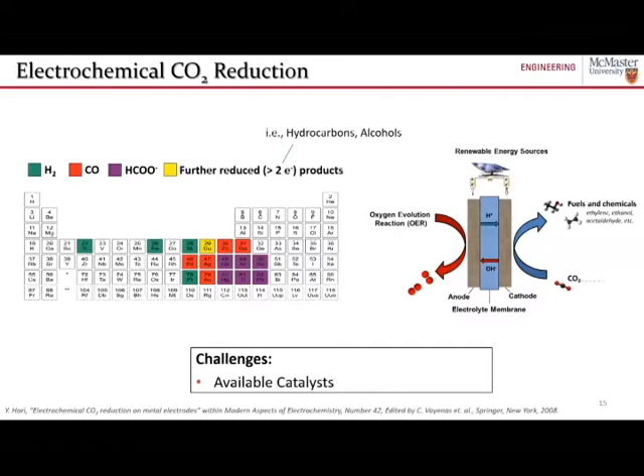So any catalysts that produce hydrogen are already non-candidates because they're ultimately producing a product that for these purposes we're not interested in. Some catalysts are very good at producing carbon monoxide. A lot of times those are expensive catalysts, things like palladium, silver, gold. There are a few catalysts that are very selective for producing formic acid. One thing about formic acid is it's really great if formic acid fuel cells can become a sustainable energy technology, but right now they're not quite there. So the global market size for formic acid is just not huge that a technology of this nature would make a large impact in terms of global CO2 emissions.